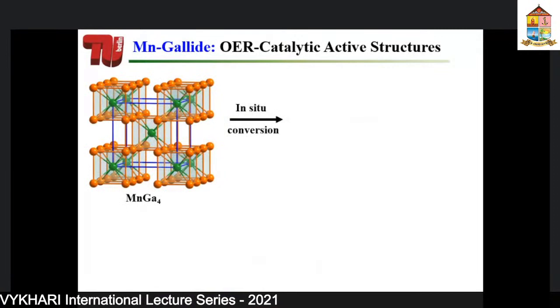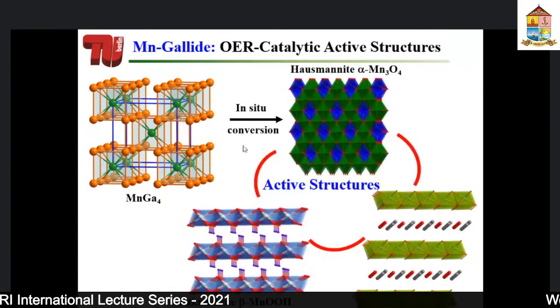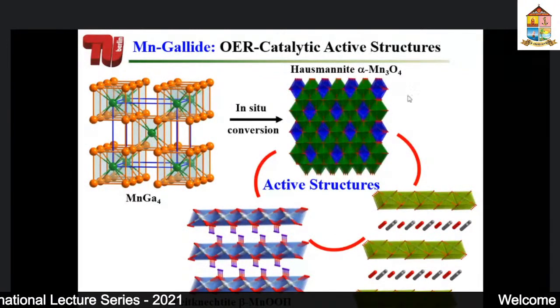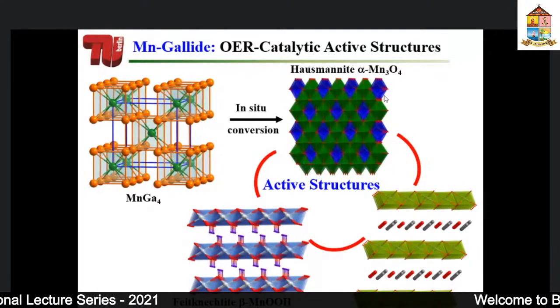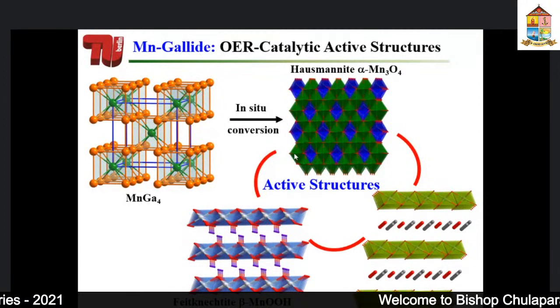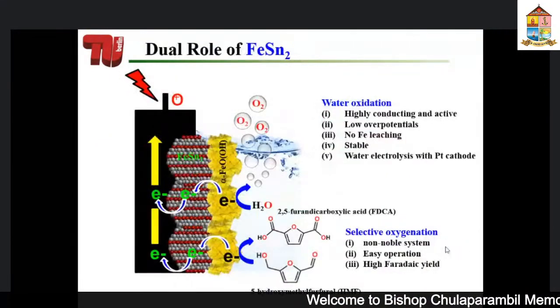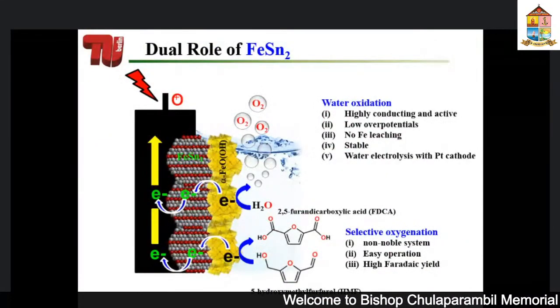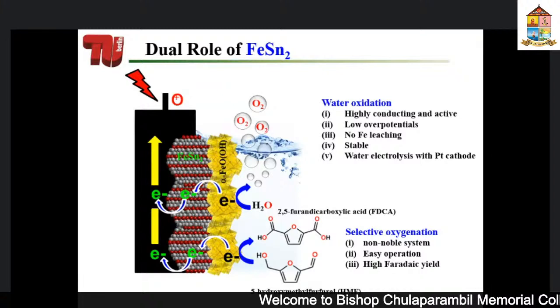So again, to show you how it looks, you start with a very nice structure, and at the end you are forming an active structure which is composed of these three: Mn3O4, delta MnO2, and beta MnOOH. And we also could identify how the whole reaction mechanism goes. So it first forms this particular phase, and then it goes to this phase, and finally it ends up in this phase.